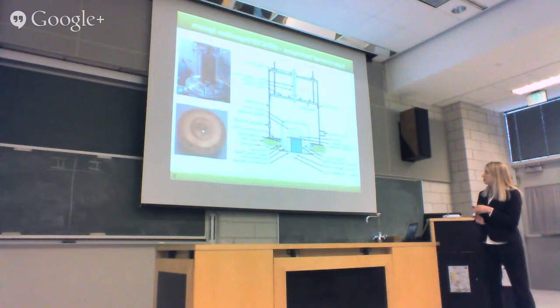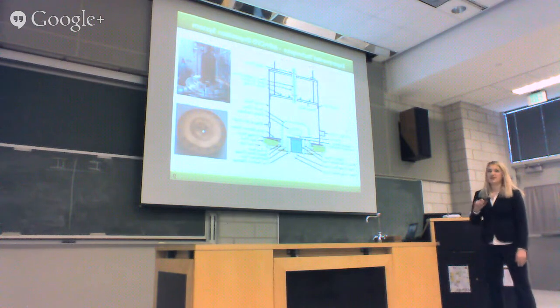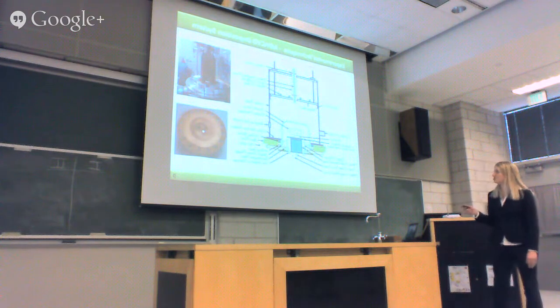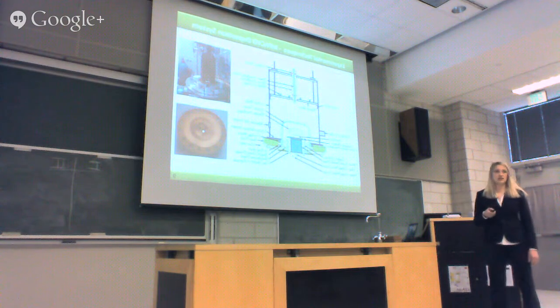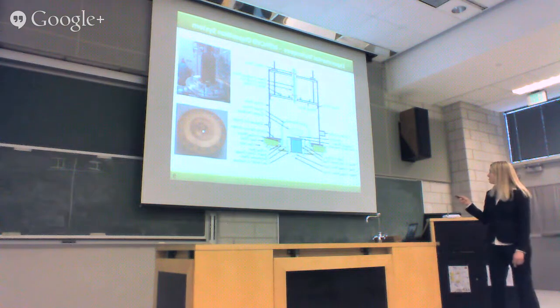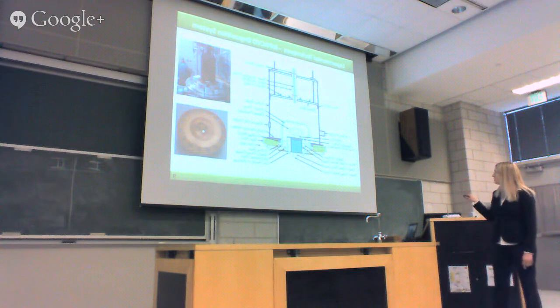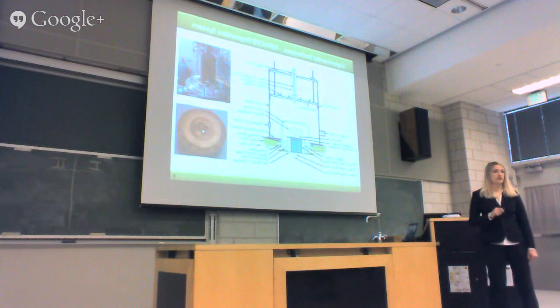So how do we grow diamonds? Well, we grow it by microwave plasma assisted chemical vapor deposition. Essentially, we have an energy source, which is microwave power, and we contain it within a brass resonant chamber. We have a probe that excites in this chamber a TM013 mode, which has 3 electric field maxima. We take the bottom of those nodes, we enclose it inside a quartz dome, we pump all of the air out to vacuum, and then we flow in through the gas inlet only the gases that we want present in the chamber during growth.